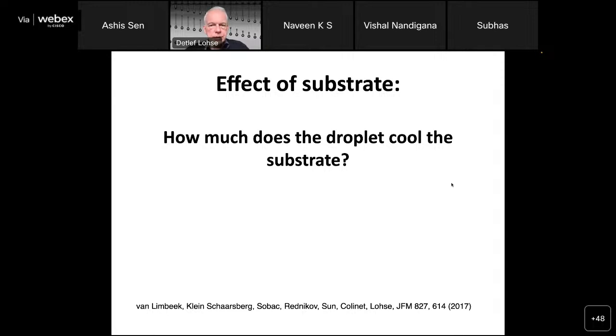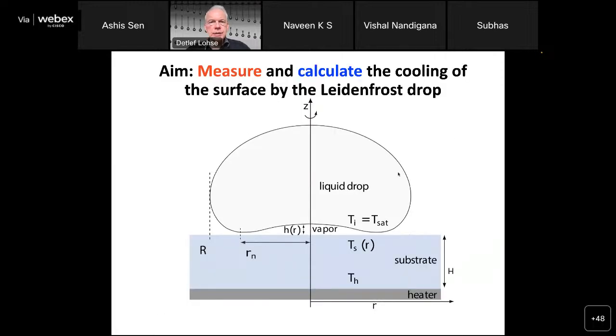The question is, can you measure this? So how much does the droplet cool down the substrate? And in fact, Michiel van Limbeek did succeed to measure it. I must say, I was pessimistic about it. So the aim was to measure and to calculate the cooling of the surface by the Leidenfrost droplet. So here you see the situation. Here we have our liquid droplet, and here you have the heater at temperature TH, but the temperature up here, where you are in closer contact to the substrate, is lower. And can you calculate this and can you measure this? Well, on calculation, I was optimistic. On the measurement, I was pessimistic. And what Michiel did is that he did succeed.